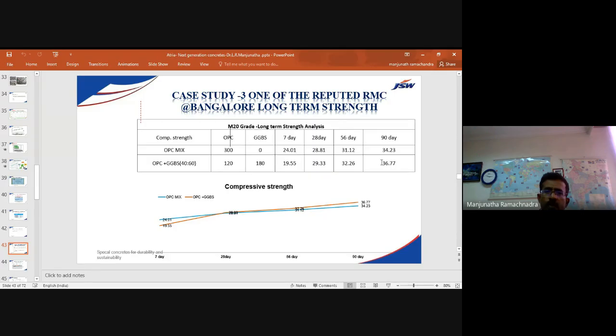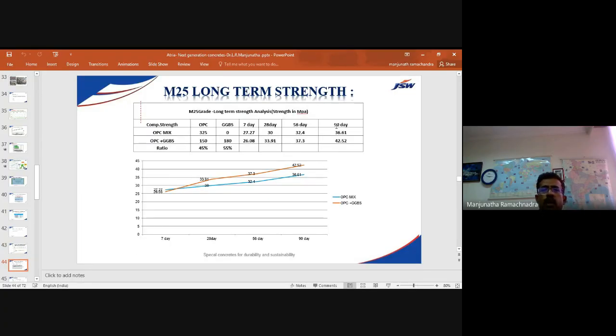The GGBS mix with 60% GGBS has given 36.77 MPa. So not only saving cost, but also durability, performance enhancement, longer strength. Similar way, we have done for the M25 grade concrete. You can see a clear upper graph, with the improved compressive strength compared to the pure OPC mixes.